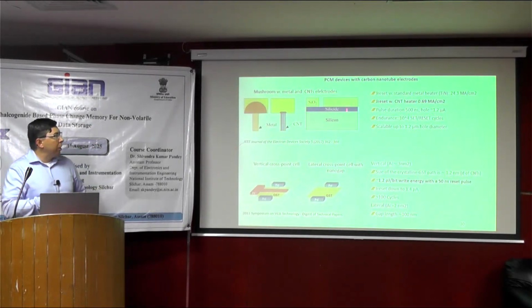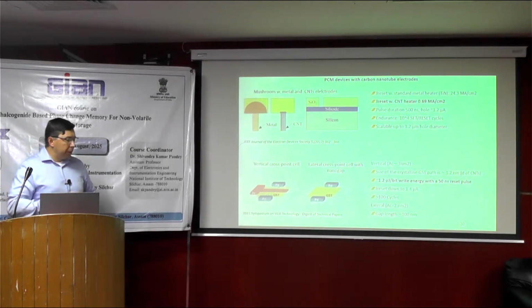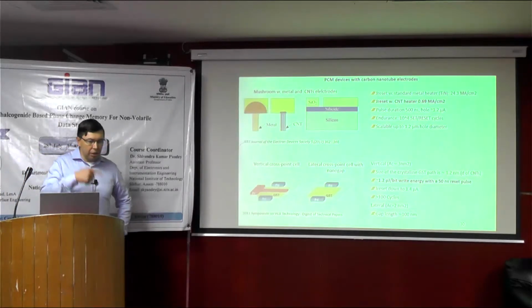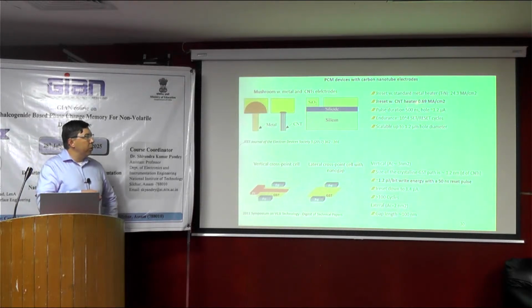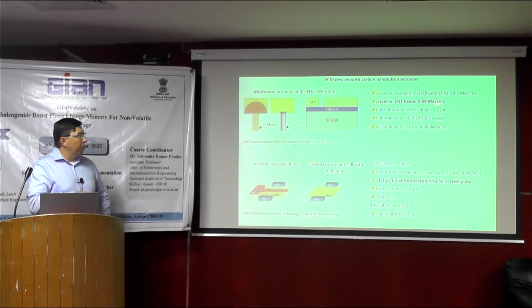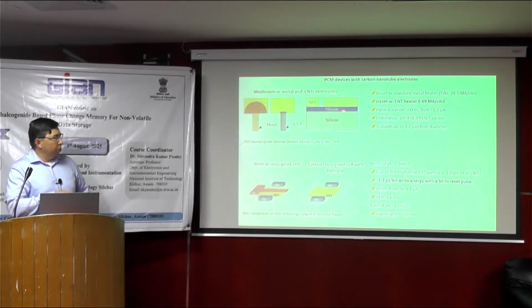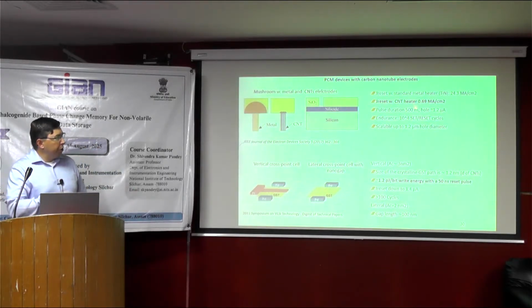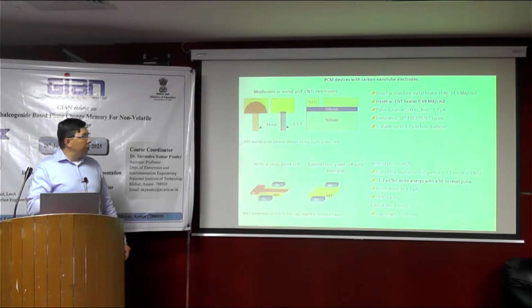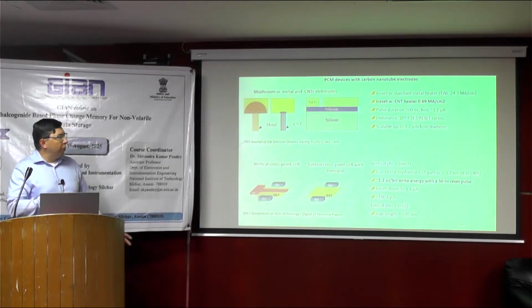But if you use an improved heater using CNTs, which has higher conductivity, then you get values of on average 0.7 mA per square centimeter. Here they also used a pulse duration of 5 nanoseconds. We want 100 nanoseconds, but just to achieve this value, they needed to use it. Endurance was 10 to the 4. It's also not good, but it was scalable in the hole diameter.